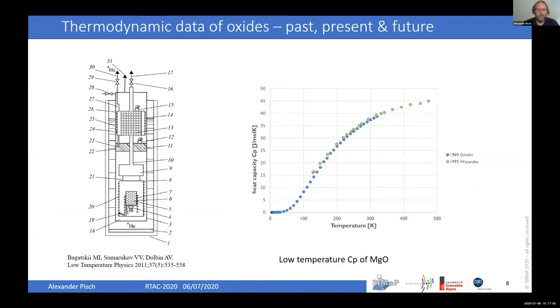And so you have two techniques. You have the low temperature adiabatic calorimetry, one example on the left side of a Russian equipment. There are also some American and French equipments. But one characteristic is that there aren't many of these adiabatic calorimeters around anymore. On the right side, you see a result for magnesium oxide, from a few Kelvin up to room temperature, and you can then derive the standard entropy at room temperature from this equipment. This equipment is very precise from a measurement point of view. The main critical point is the sample, and I will show you a little bit later a result on lime, why this point is critical.